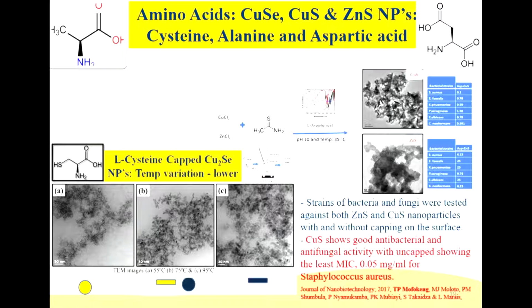You've got copper selenide, copper sulfide, and zinc sulfide. You can see down here that when you're using L-cysteine, particles are not as controlled as when you're using HDA, for example, but there's still some change in the way they form, primarily driven by the different functional groups. You've got the carboxylic acid group and the amine groups, and therefore that doesn't orient particles in one direction, so you end up with rather non-spherical particles. The same applies to the aspartic acid that is used there.